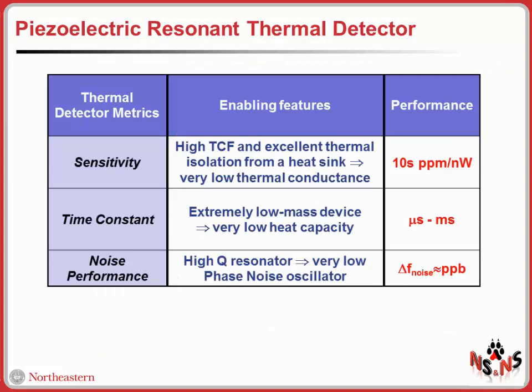Now if we look at the most important metrics for thermal detectors, which are sensitivity, time constant, and noise performance, we see that these kinds of piezoelectric resonant thermal detectors really have some quite unique enabling features. In fact, it's possible to achieve high sensitivity thanks to the intrinsically high temperature sensitivity of the device, but also thanks to the fact they can be made very well isolated from the heat sink, so at very low thermal conductance, which means high thermal sensitivity. The time constant is very low, given the very low heat capacity of the structure. So we are talking about a micro-nanomechanical device, so very small thermal mass, which means time constants in the order of microseconds to milliseconds.